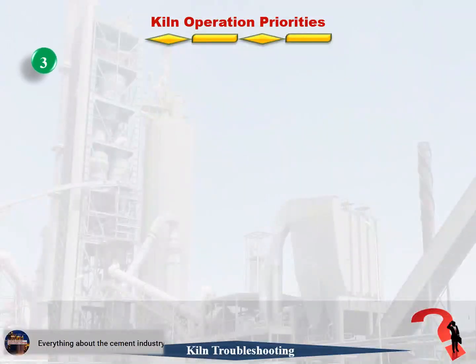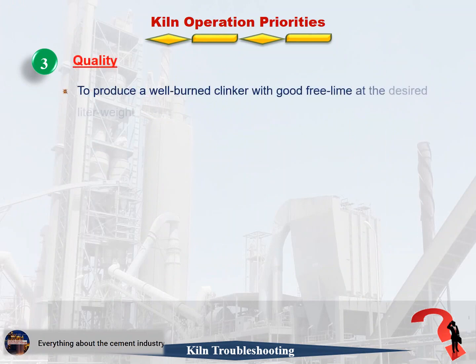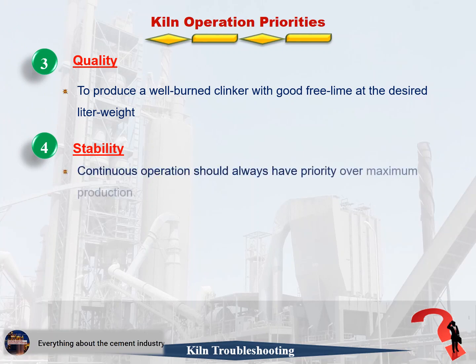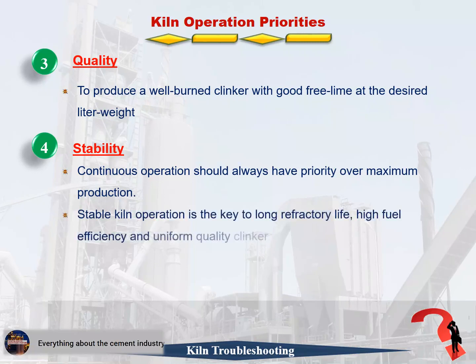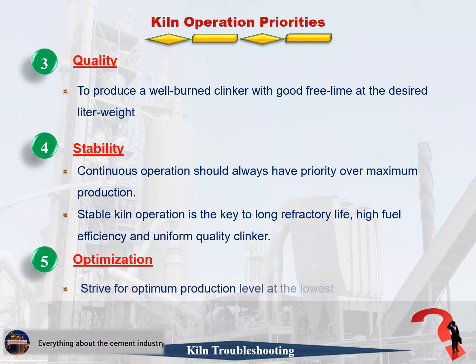3. Quality. To produce a well-burned clinker with good free lime, at the desired liter weight. 4. Stability. Firstly, continuous operation should always have priority over maximum production. Secondly, stable kiln operation is the key to long refractory life, high fuel efficiency, and uniform quality clinker. 5. Optimization. Strive for optimum production level at the lowest possible cost.